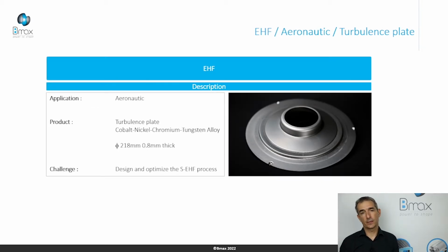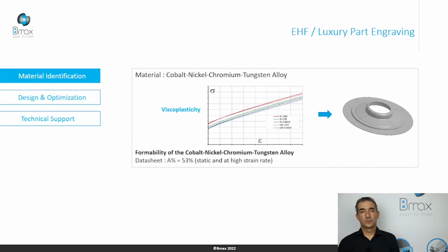The material is a cobalt nickel chromium tungsten alloy, 218 mm in diameter, 0.8 mm thick. The objective is to design and to optimize a hybrid process as a stamping EHF process. It's a Bmax patent. The first step consists of characterizing the material in static and in dynamics. This cobalt nickel alloy is sensitive to the strain rate. There is a viscoplasticity, and we can expect an enhancement of the formability. We use all this material data to represent the behavior of the sample on the right.